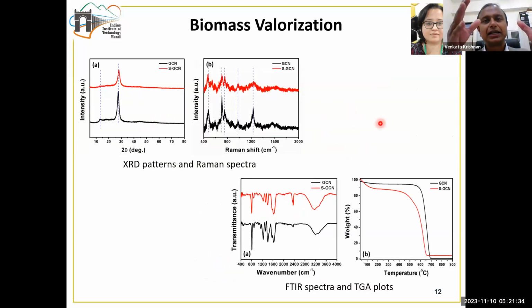Then whenever we prepare a catalyst, first and foremost, we need to know whether our preparation is successful or not. For that, we have to do certain characterization of the material. So we have done the X-ray diffraction characterization of the normal graphitic carbon nitride and also the sulfonated graphitic carbon nitride. And from the peak positions and by comparing with the literature values, we are quite certain that the graphitic carbon nitride material has been prepared. However, the sulfonation cannot be evidenced from the XRD pattern. For that, we need to do the functional group analysis, which has been done using the Raman spectroscopic technique and also the FTIR spectroscopic technique, the infrared radiation spectroscopic technique. So based on this, we are able to figure out that the sulfonyl groups are also present on this material.